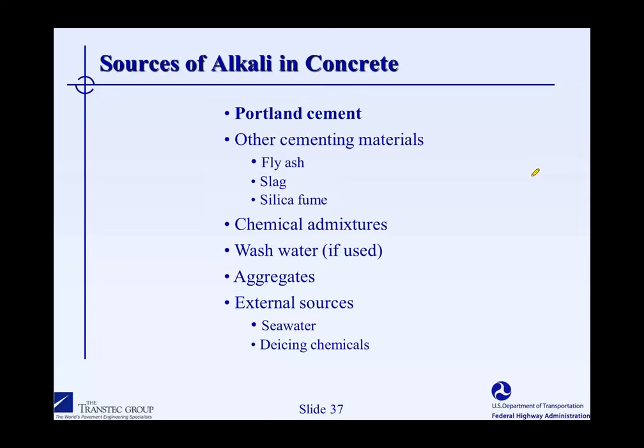Other cementing materials that we use in concrete, particularly fly ash, can themselves contain relatively high amounts of alkali. Despite this, they tend to be effective in controlling ASR. Even though they contain alkalis themselves, they tend to combine with some of the alkali from the Portland cement and actually prevent expansion rather than contribute to it. However, we'll save that discussion until next week when we talk about preventive measures.